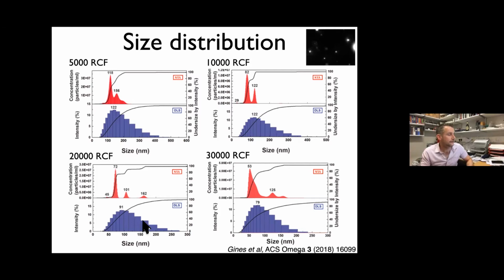So the blue ones here are the DLS spectrum, and the red ones are what we call NTA. Now, NTA is another light scattering technique invented by a British company called Nanosight, that's now bought by Malvern, actually, another British dynamic light scattering company. You see what happened there. And what they do is they create a kind of plane of scatter with the laser, right? So they have a scope with a very, very fast camera looking at the laser scatter move as a function of time. And then they track the motion of the particles with a computer. And then you can build up a distribution of the actual particle sizes. And so the nice thing about that is you can see components underneath the DLS spectrum. But this is kind of horses for courses, because this technique won't work with too strong concentrations. Then you just have to use DLS. Also, you can't see below 20 nanometers, so it's useless for the detonation material, unfortunately.